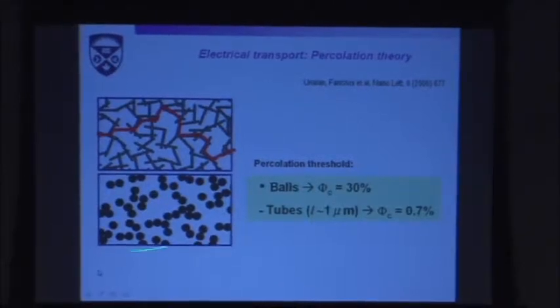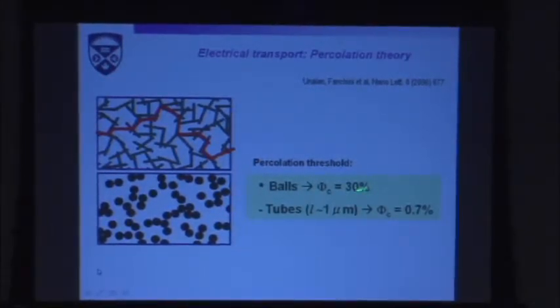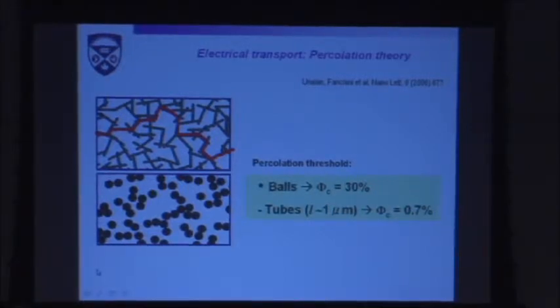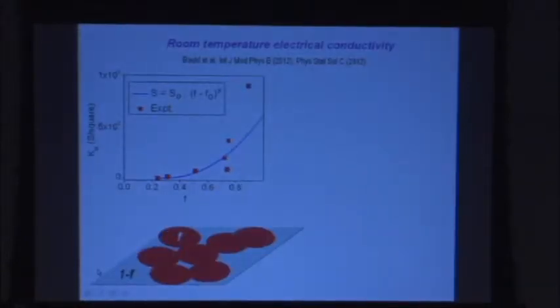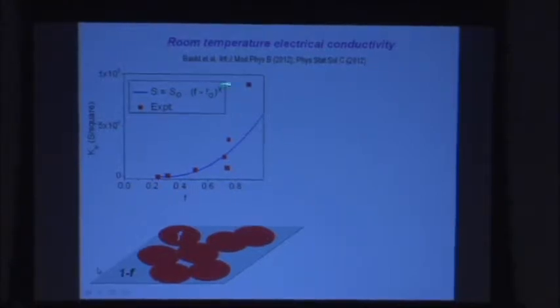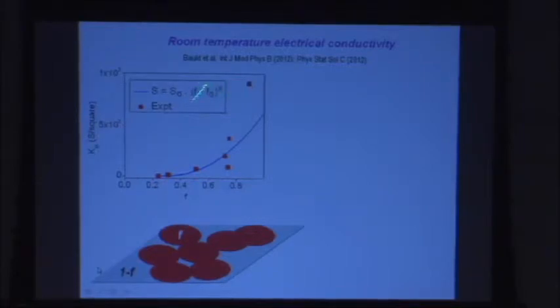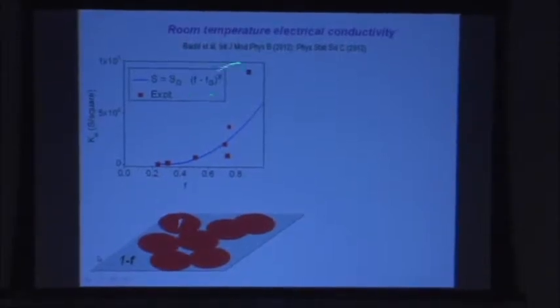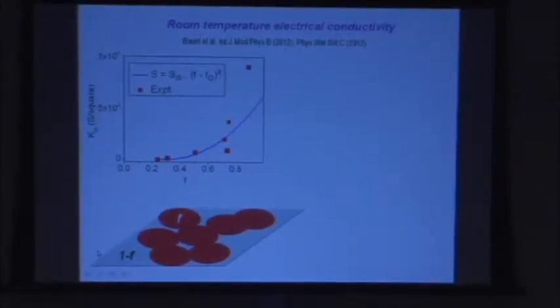That controls your properties. How dense is your patchwork of graphene flakes? If you are below the percolation threshold, so these are sparse and individual and separated, the conductivity is 0 or tends to 0. At the percolation threshold, you start to have conductivity and it increases above. This is generally expressed by a power law like this. The conductivity is equal to the conductivity of the individual flake, that obviously matters, multiplied by a power. F0 is the percolation threshold, F is the fraction of covered area that has to be above the percolation threshold, otherwise this relation is not true. At the percolation threshold, this term is 0, so you don't have any conductivity, and there is an exponent that is related to the dimensionality of the system.